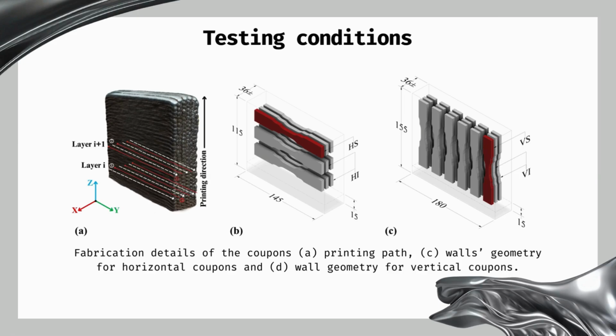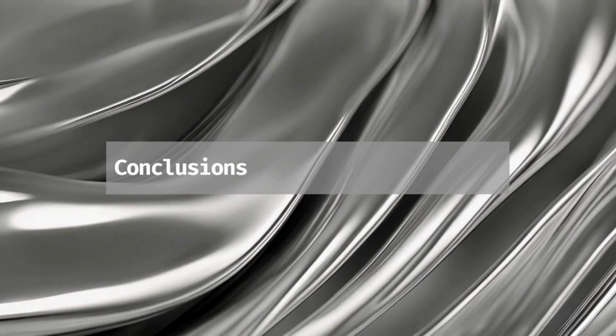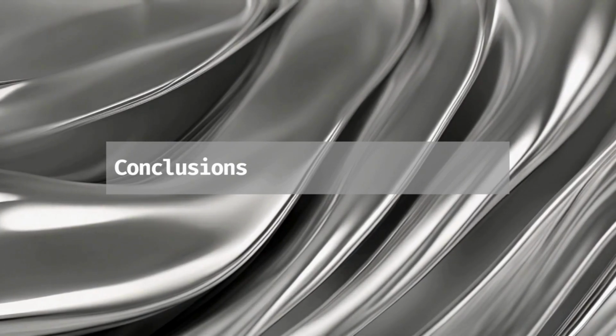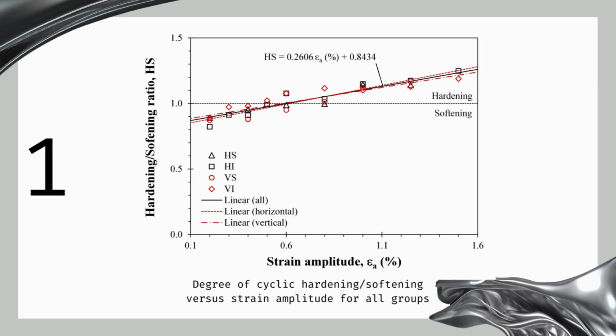Central to our investigation was the impact of orientation and through-thickness location on fatigue behavior. So, after the production of the walls, coupons were extracted horizontally and vertically across 3 thickness locations. The conclusions of our study can be summed up in 6 points.